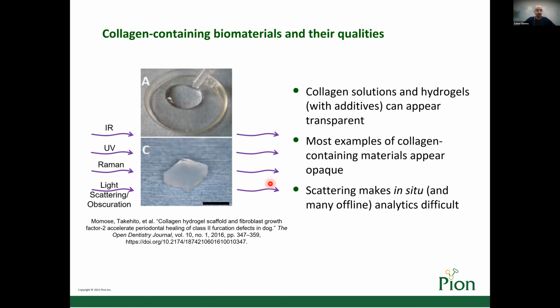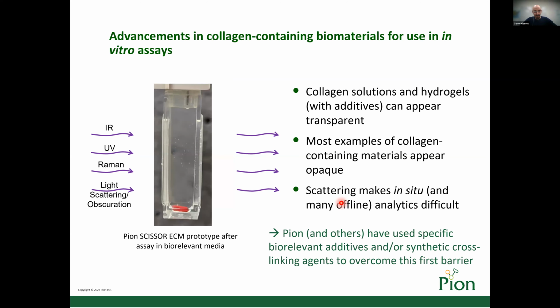As mentioned before, there's a lot of spectroscopic analysis that wants to happen within these materials, especially after you introduce a pharmaceutical agent into them. Since this time, Pion and others have come up with little tricks in order to form solid materials that have a significant collagen concentration that are also optically clear when it comes to these different types of spectroscopic analysis. And now using these types of materials, like the ones found in our scissor, although this is a collagen-based prototype, these types of materials are now used to understand what happens during an injection, after injection, and diffusion away from an injection site.